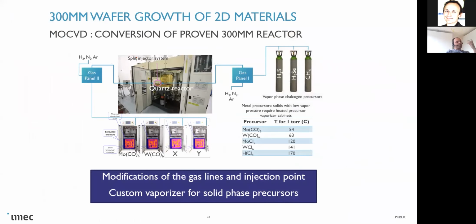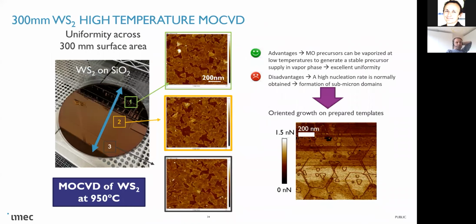But at imec, based on that paper and so on, we also chose to work on an MOCVD reactor. So we refurbished one of the old EPI reactors we had in-house, and we redesigned the whole reactor to make it compatible to TMDC MOCVD, and to make sure that we could work with these solid state precursors. The big advantage, this was one of the first wafers that came out, so you can immediately see that it's a very uniform deposition if you have the right conditions. So this is a 300 millimeter wafer.